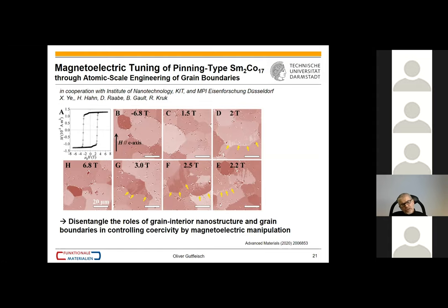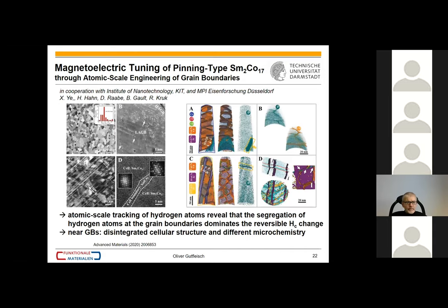And that is something people normally don't look at because people only look at the cellular structure. So, and what we can show then with a very nice advanced atom probe by the colleagues in Düsseldorf is that the grain boundary in 217 is the phase which preferentially absorbs hydrogen significantly, and that acts then as the nucleation site where magnetization reversal propagates. And that is why we are able to switch to such a large extent, by 1.3 Tesla, the coercivity reversibly by hydrogen absorption and desorption. So that's very interesting, to use hydrogen as a probe to understand nanoscale magnetism better.